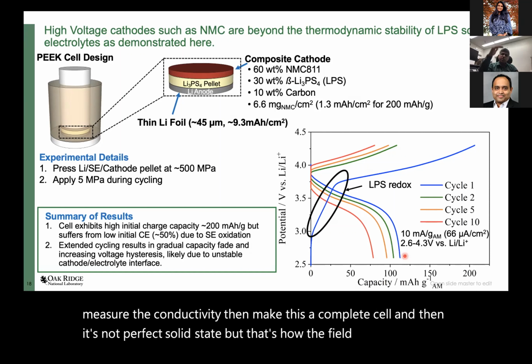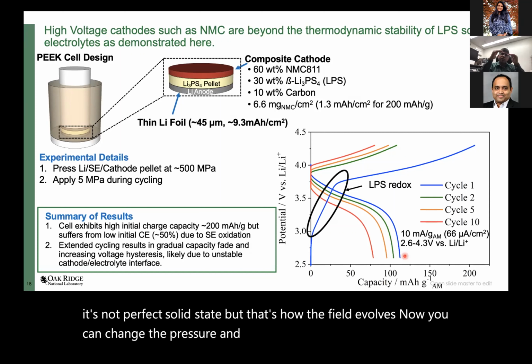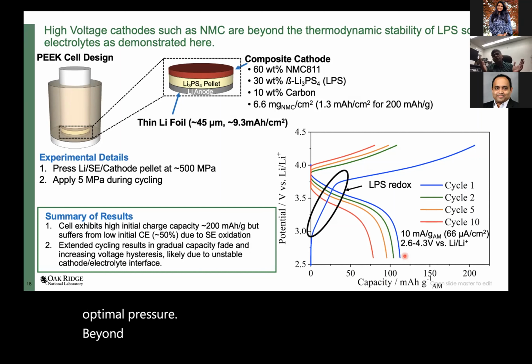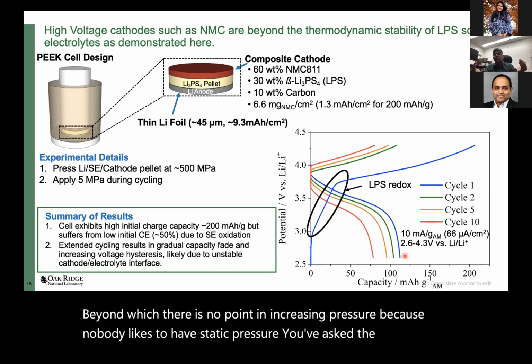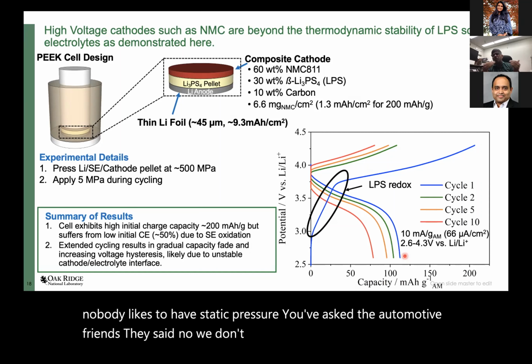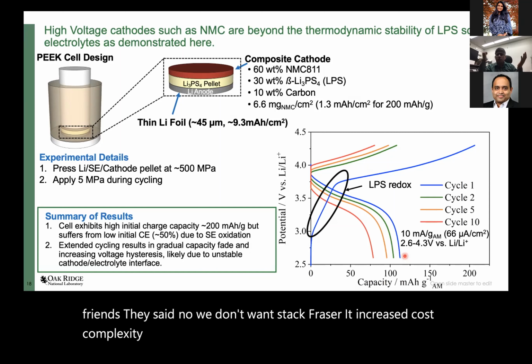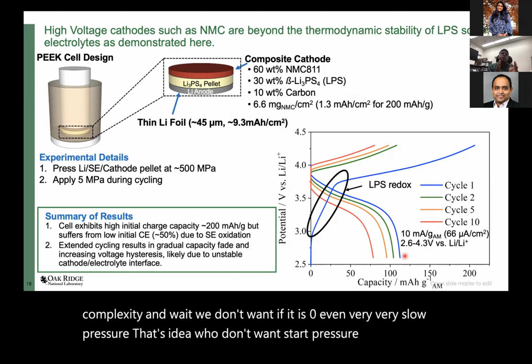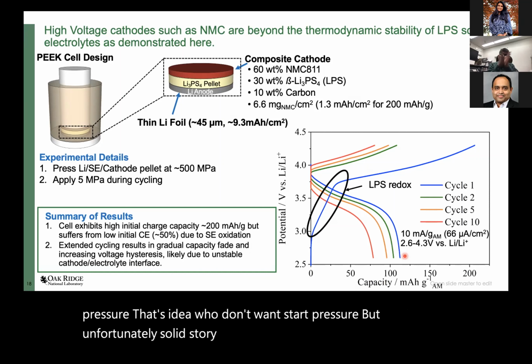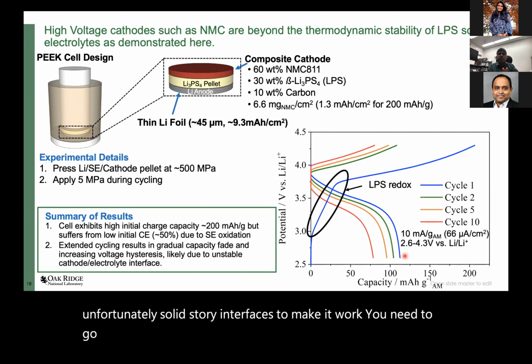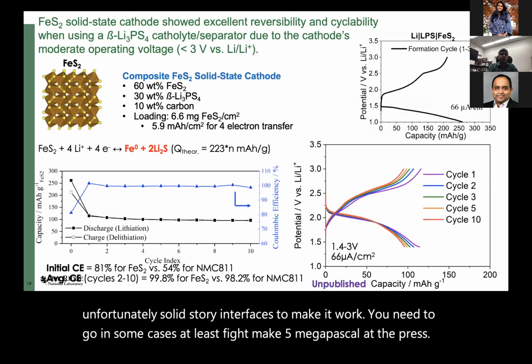Now you can change the pressure and see whether you have hit the optimal pressure, beyond which there is no point in increasing pressure, because nobody likes to have stack pressure. If you ask the automotive friends, they say, no, we don't want stack pressure. It increases cost, complexity, and weight. If it is zero, even very, very low pressure, that's ideal. We don't want stack pressure. But unfortunately, for solid-solid interfaces to work, you need to go in some cases at least 5 megapascal of pressure, for sulfides at least.